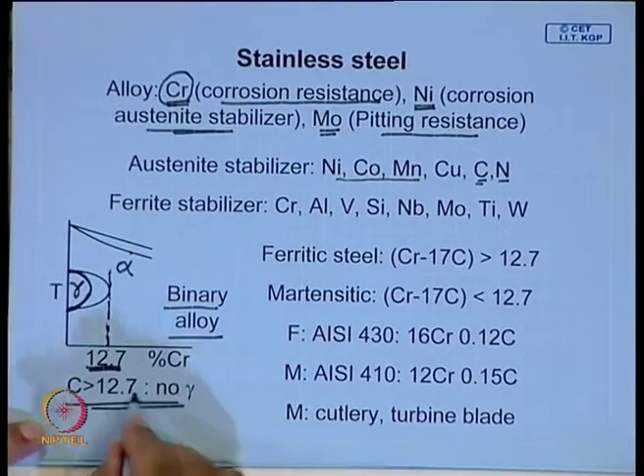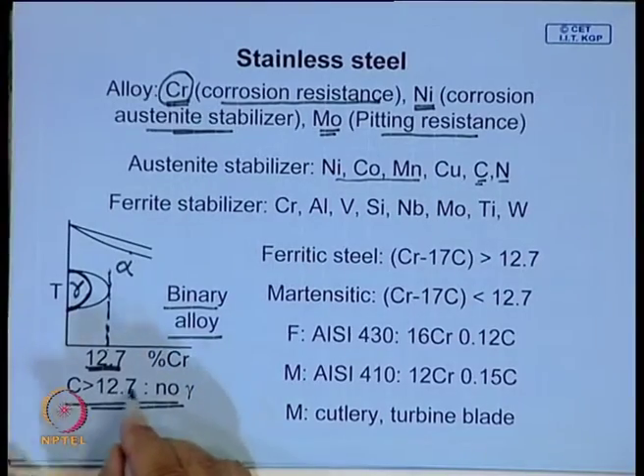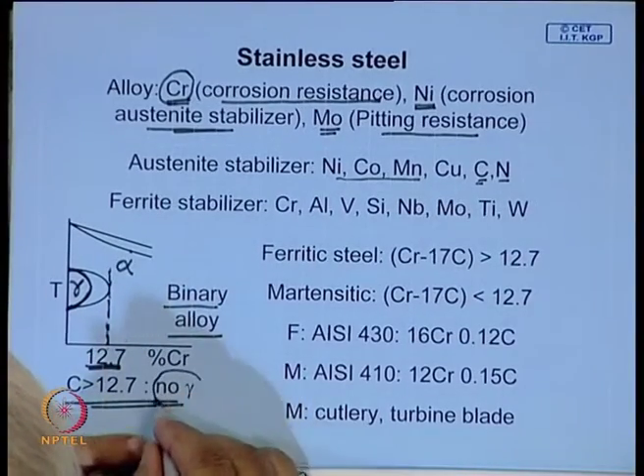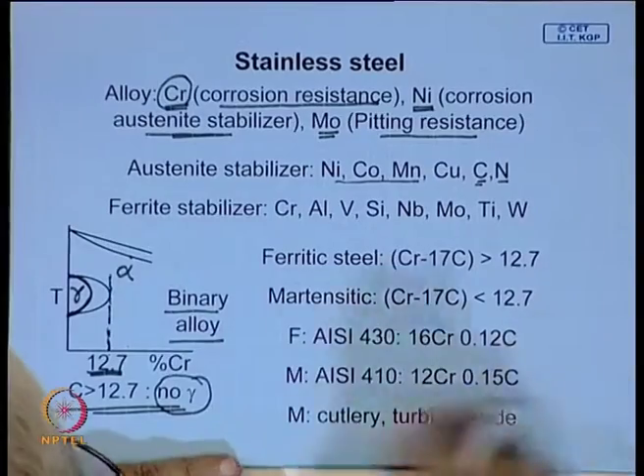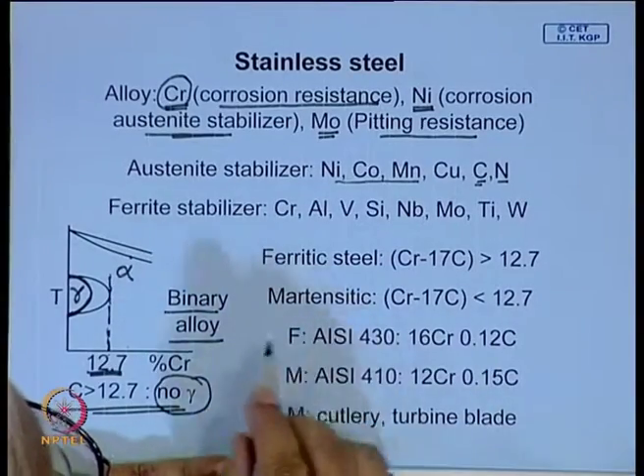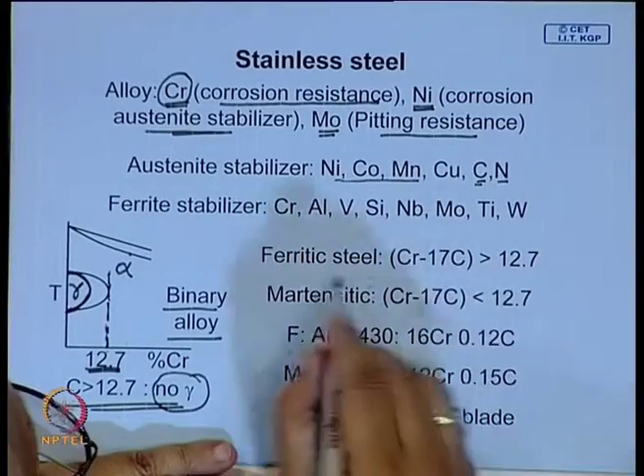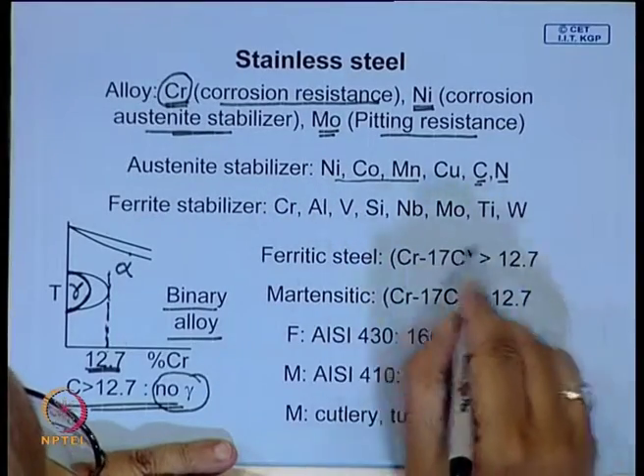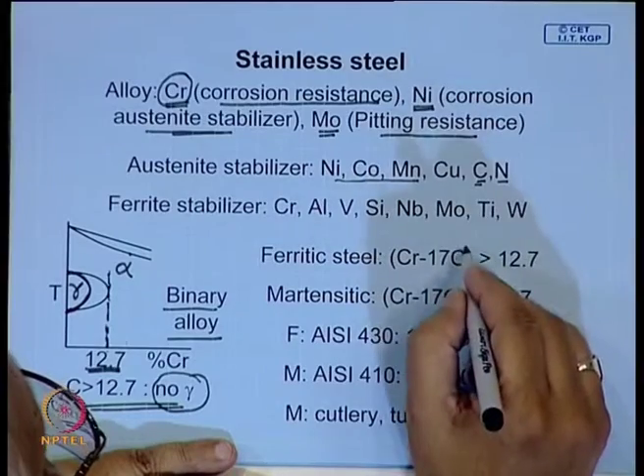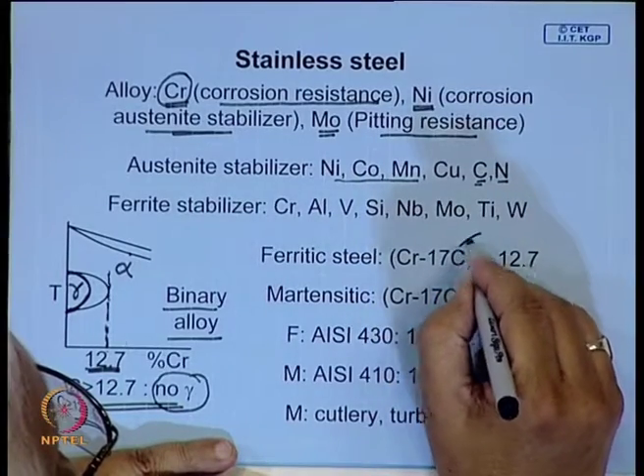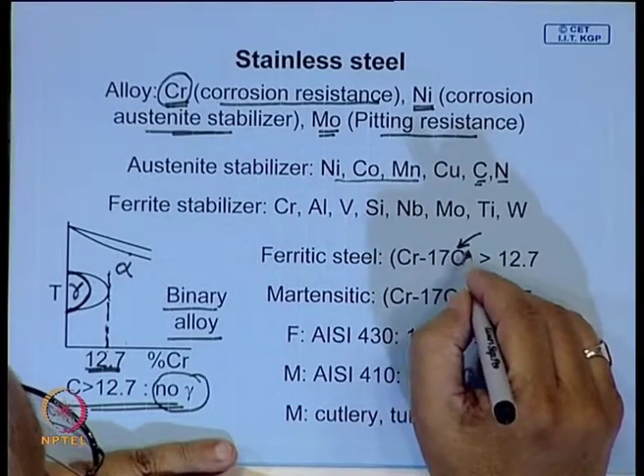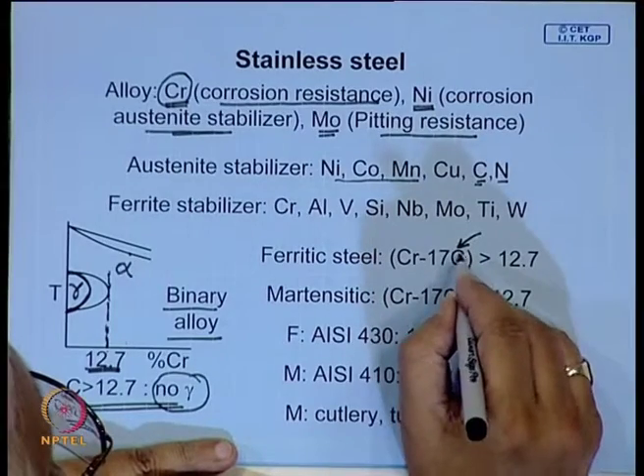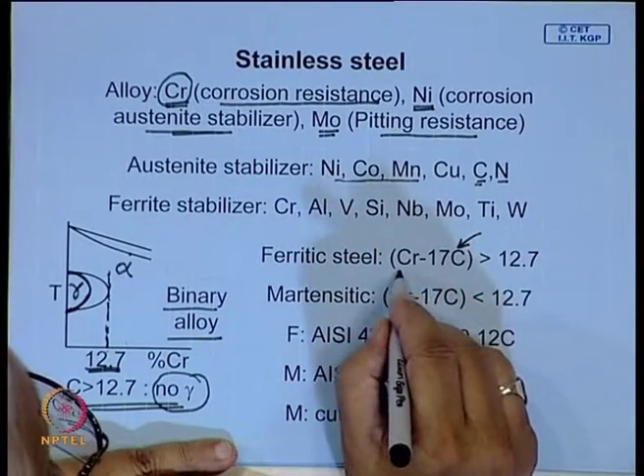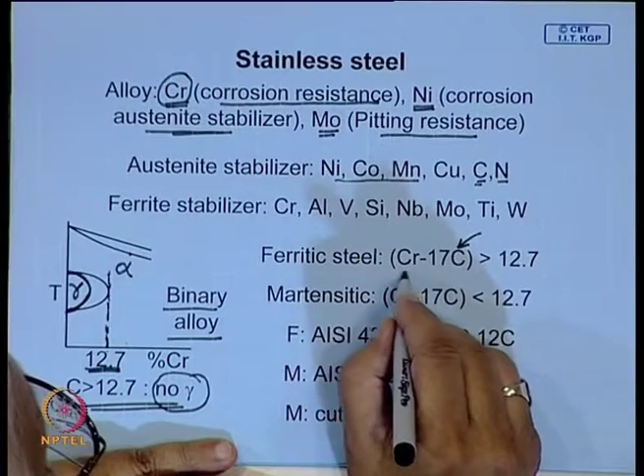So, this is important to remember. If it is greater than 12.7, then you have no chance of forming austenite. So, if you have a stainless steel where you have carbon, we have seen this is an austenite stabilizer. So, if you have some carbon in the steel, effective chromium concentration goes down.